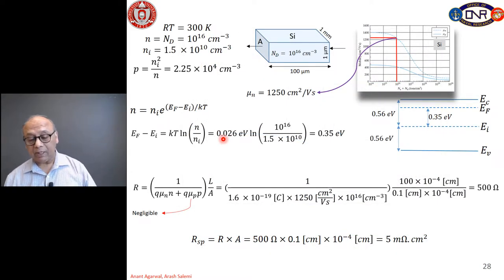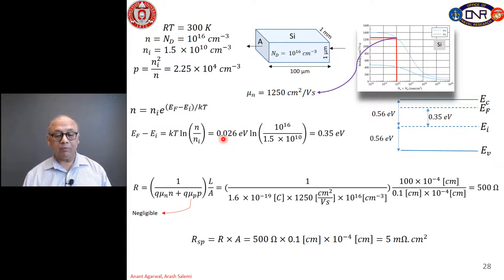Let's work through this example calculation to show you how we use these mobility numbers to calculate the resistance of a rectangular piece of semiconductor. So in this case, we have a rectangular piece of semiconductor with a cross-sectional area A and a doping of 10 to the 16 per centimeter cube n-type. D stands for donor, and the length of this slab is 100 micron and the width is 1 millimeter. So then the question is, can we calculate the resistance of this semiconductor piece if the current is flowing as shown by the arrows? And we're doing this at room temperature. So we know that the number of electrons is going to be equal to the number of dopants. So that is 10 to the 16 per centimeter cube.